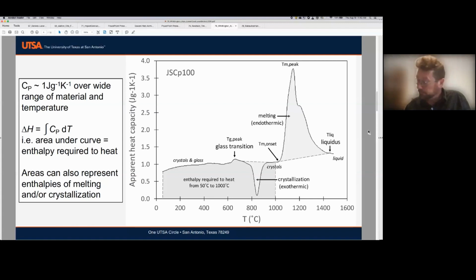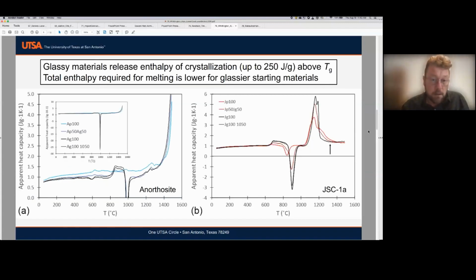Next slide, please. Okay, so basically, we can see here anorthosite on the left, JSC1A on the right. The glassy materials have these big crystallization troughs where they release around 250 joules per gram, maybe higher, once they get above the glass transition. The key thing we noticed overall is that the total enthalpy required for complete melting, going up to the liquidus, is still lower for glassier starting materials. Next slide, please.